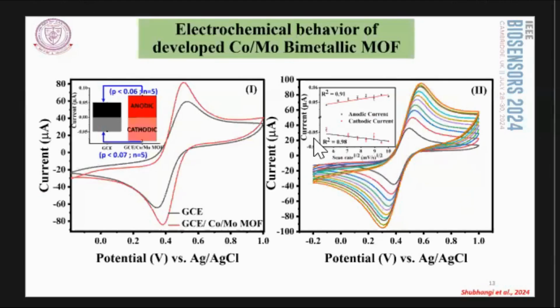The electrochemical behavior of the cobalt molybdenum bimetallic MOF was investigated through different routes. The first being the cyclic voltammetry method, where the bare electrode surface, when coated with the electrodeposited cobalt molybdenum MOF, saw an increase in charge transfer characteristics by almost 1.5 times compared to the bare electrode. Apart from that, a scan rate dependent study was conducted where the scan rate was varied from 10 millivolt per second to 100 millivolt per second to understand the diffusion controlled charge transfer behavior of the electrode surface. And we found a linearity in the current with the square root of the scan rate, which proved our hypothesis for diffusion controlled charge transfer, with an R square of 0.91 and 0.98 for the redox process.